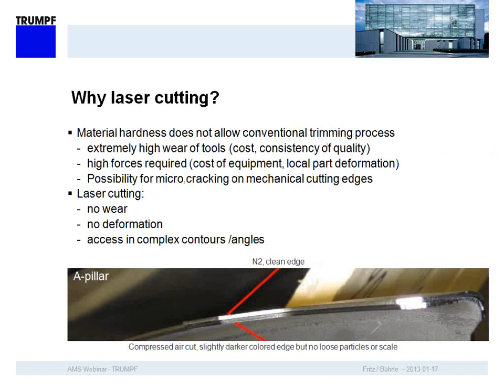So why do we do laser cutting instead of the conventional hard trimming press or trimming in the die? Because what we saw, there's an extremely high wear of the tooling. So a lot of cost involved to repair the tools, to keep them running. Downtime, there's pretty high forces required. That means big presses, which also cost a lot of money. And also the hydrogen embrittlement when mechanically cutting edges of already hot stamped components. With the laser on the other side, we don't have any wear on the tooling, we don't have deformation on the part, and we can also have accessibility with our laser heads into very complex contours and very complex shapes.